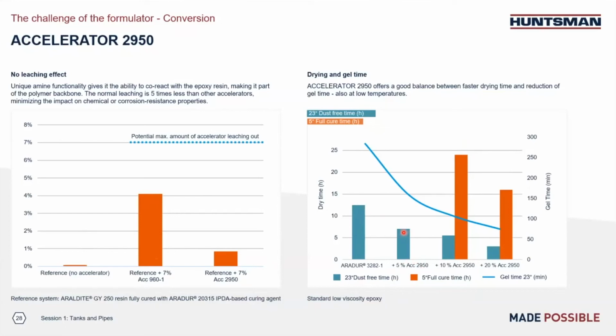At the lower temperature, such as 5 degrees, the epoxy and amine reaction is getting slower, right? So we need to use more to really kick up the speed. If we're using 10% accelerator 2950, you can see now we measure the full cure time, and the full cure time is less than 24 hours.